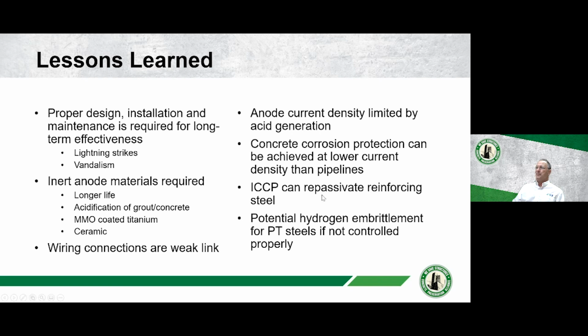Impressed current cathodic protection can repassivate reinforcing steel, which is very unique because reinforcing steel is in a very alkaline environment, and you didn't see the same type of behavior in soil with pipelines. Nothing passivated; it just didn't corrode. Now, what I'm talking about is repassivation. If you reestablish the passive film on the rebar, you can turn off your impressed current system for a year or more, and it still won't have any corrosion activity. So this generation of hydroxyl at the cathode reinforces the naturally occurring passive layer on rebar in concrete.